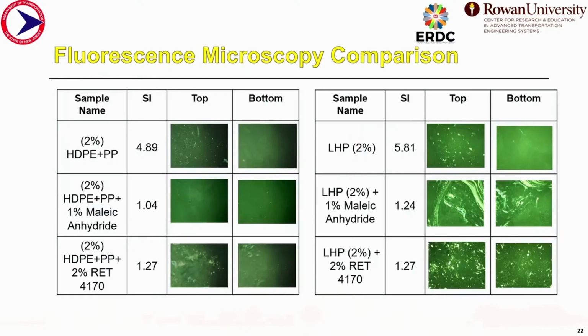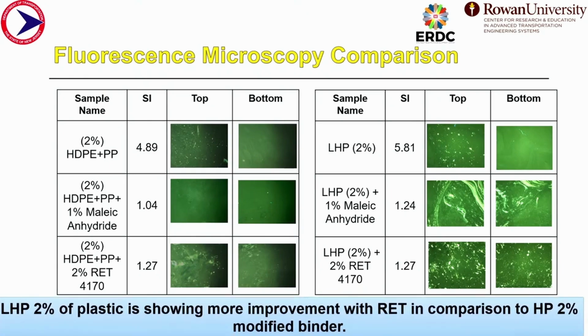So these are the different fluorescence microscopy images that we get for the storage stable binder from the separation index values. Here we can see for the HP plastic and LHP plastic with 2%, both the stabilizers are performing well. However, if we look deeper, with the HP plastic the polymer distribution is not that visible or clear. On the other hand, for LHP plastic with the RET stabilizer, the distribution of the polymer or the plastic is very visible at both top and bottom. So from here, we can see the LHP 2% plastic is performing better with the RET than HP 2% plastic.